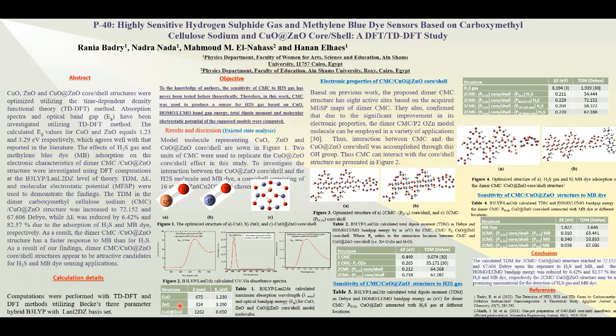Based on our previous work, it is concluded that metal oxides can interact with CMC throughout the hydroxyl group of CMC. Accordingly, there are two possibilities for the interaction of CMC with the core shell structure. The first interaction mechanism occurs via the hydroxyl group of the CMC and the oxygen atom of the shell. However, the second interaction mechanism proceeds throughout the metal atom of the core shell structure as presented in Figure 3. Table 2 presents the total dipole moment values and the HOMO-LUMO energy for these two interaction mechanisms, and it confirms that the interaction proceeding throughout the oxygen atom of the shell is the most prominent one, as it has the lowest HOMO-LUMO band gap energy.